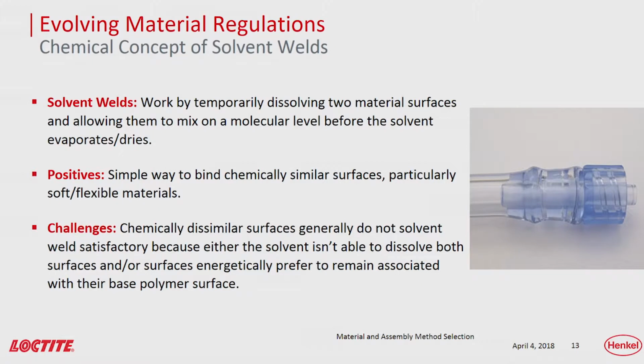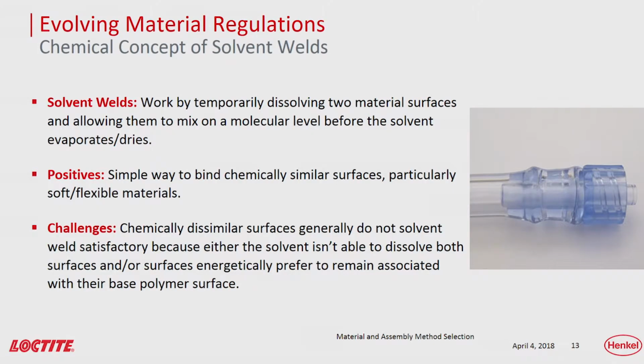The positive of this is it's a simple way to chemically bond similar surfaces, particularly soft, flexible materials. And so a solvent can be added to the surface, kind of welded together, and then evaporated. Some of the challenges associated with this is that chemically dissimilar surfaces, as Jason just mentioned, generally do not solvent weld satisfactorily, because either the solvent isn't able to dissolve both materials in a similar fashion, or the surfaces energetically prefer to remain associated with their base polymer surface.